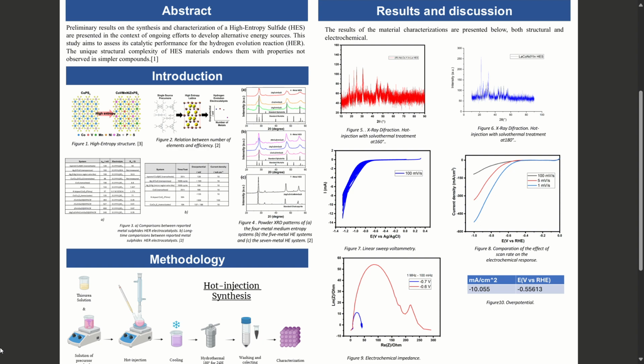Two, electrochemical performance. In linear sweep voltammetry, the catalyst demonstrated competitive overpotentials to reach the benchmark current density of 10 milliamperes per square centimeter. Compared with several reported sulfides, our high-entropy sulfide showed superior activity, placing it among the promising alternatives to noble metals. Electrochemical impedance spectroscopy revealed low charge transfer resistance, which indicates that the material facilitates efficient electron transport during the reaction.